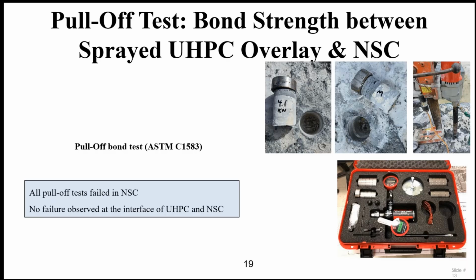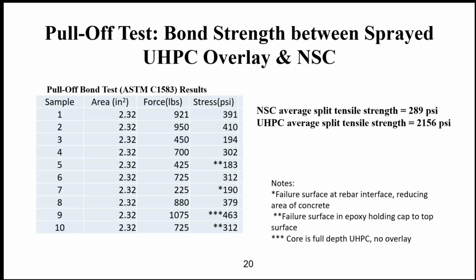So you don't have to worry about the bond between the UHPC and the conventional concrete, whether it is sprayed or cast in place. It is very strong, it is adequate, as long as you prepare the surface adequately when you apply the UHPC against it. These are just some of the numbers from the pull-off test, for example, these are the stresses that we obtained, okay? 391, 410 PSI, and so on. So like I said, we never get the failure at the interface.